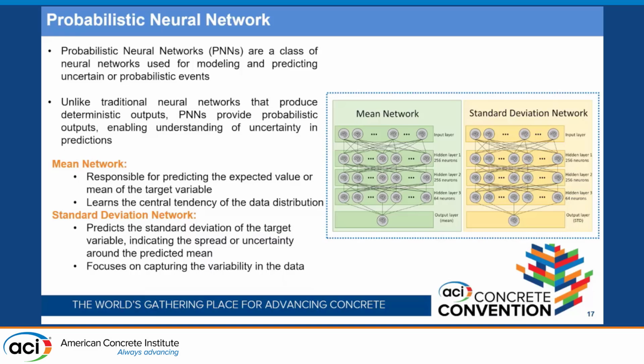So we use a probabilistic neural network, which consists of two different networks. One network is to predict the mean values, and the other network is to predict the standard deviation. In that case, we could quantify the uncertainty in the predictions that we are having.